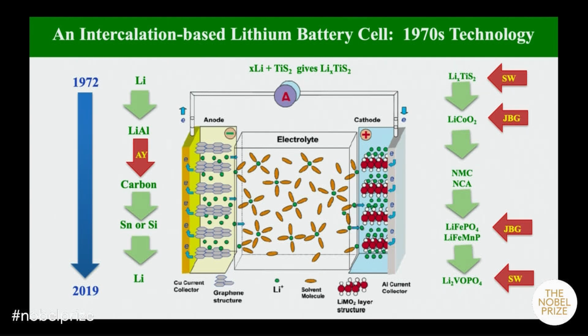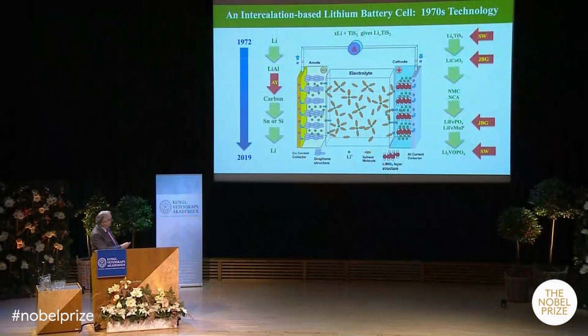Similarly, on the cathode side, we started with titanium disulfide, then went to cobalt oxide, and then in this intermediate period, people started changing out the cobalt and mixing it with nickel, manganese, and aluminum. So in there now we're going to have a whole range of different transition metal oxides.